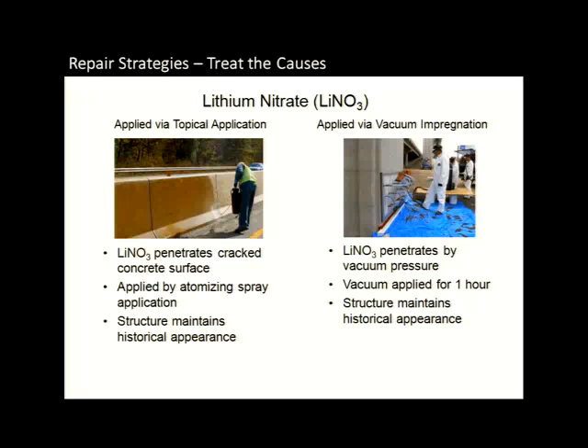So I mentioned the use of lithium salts. This is a project that I was involved in when I was at the University of Texas working on my dissertation. And you can see a typical highway jersey barrier there, or a concrete divider. You can see the type of cracking actually that we get from ASR, that map cracking. And workers going along and applying this lithium nitrate solution to the surface of the concrete.